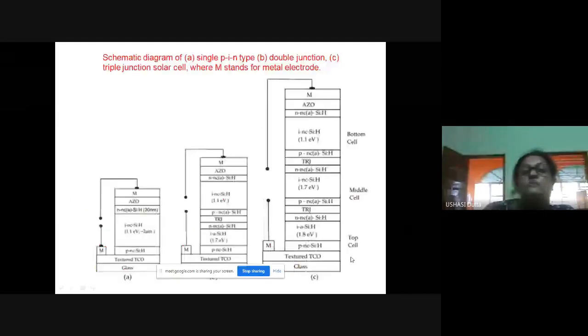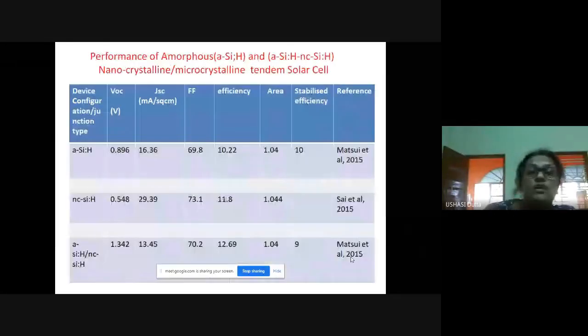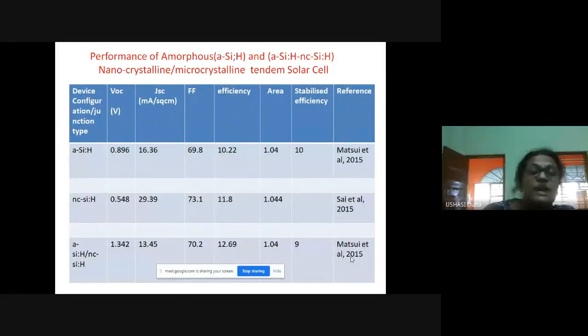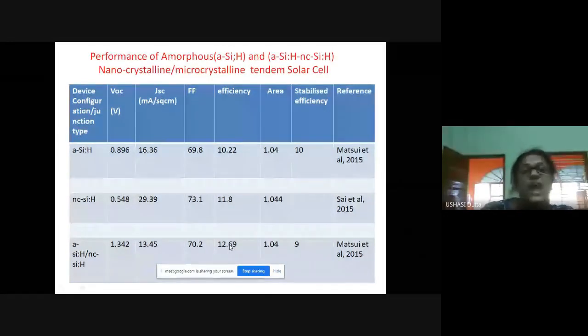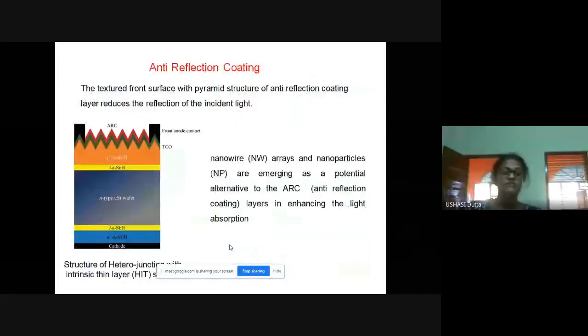This is the schematic diagram of single PIN type, double junction and triple junction solar cells, where the nanocrystalline hydrogenated silicon is incorporated. We see the performance of amorphous silicon and nanocrystalline with amorphous crystalline tandem solar cell. Here the efficiency of the amorphous silicon solar cell is 10.22%, where the amorphous silicon combined with the nanocrystalline silicon thin film raises the efficiency to 12.69%.